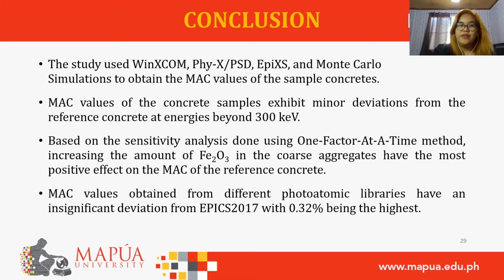After conducting the simulations and analysis of the data, several conclusions can be drawn from the study. The study used WinXCOM, Phy-X/PSD, EpiXS, and Monte Carlo simulations to obtain the MAC values and other photon shielding parameters of the sample concrete. The MAC values of the concrete samples exhibit minor deviations from the reference concrete at energies beyond 300 kiloelectron volts. Based on the sensitivity analysis done using one factor at a time method, increasing the amount of iron oxide in the coarse aggregates has the most positive effect on the MAC of the reference concrete. Lastly, MAC values obtained from different photoatomic libraries, such as XCOM and EPDL97, have an insignificant deviation from EPICS2017, with 0.32% being the highest.